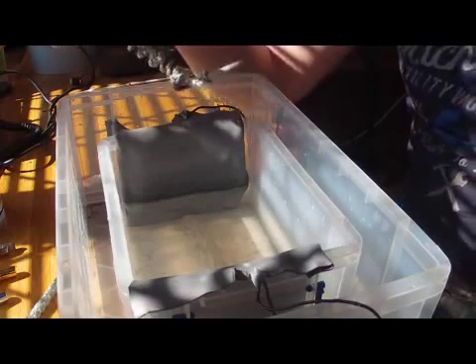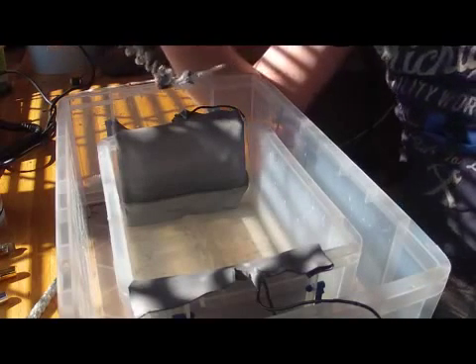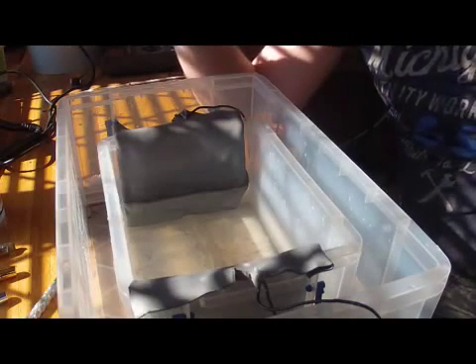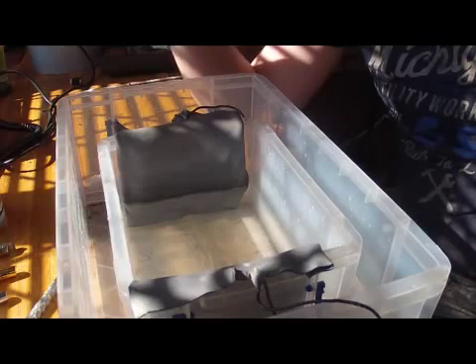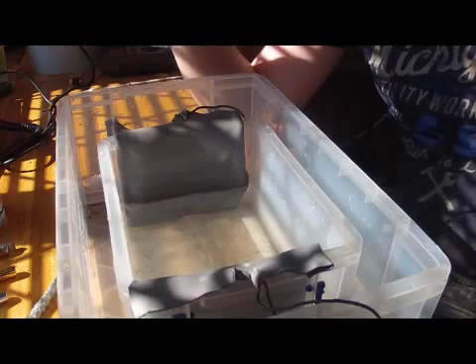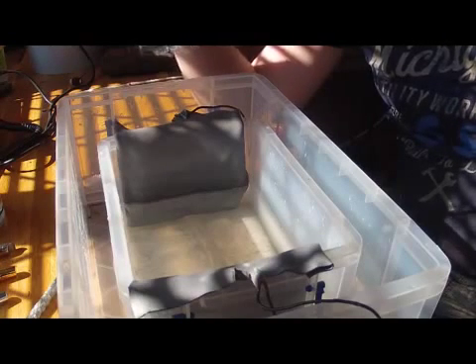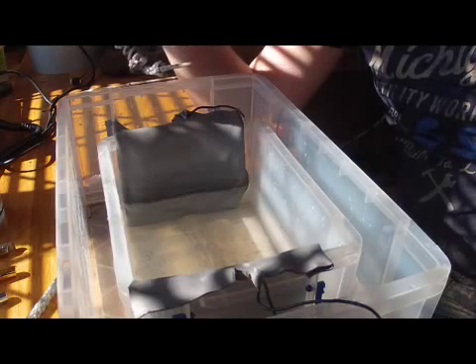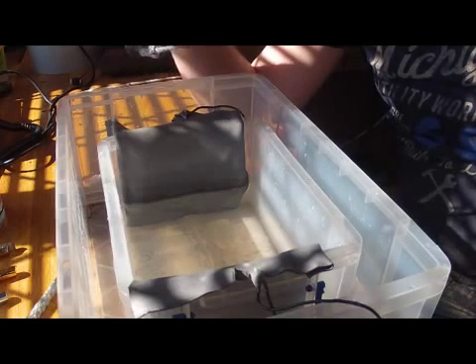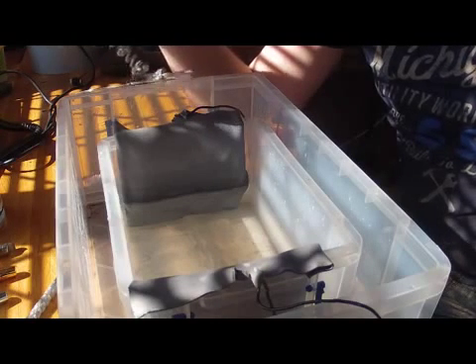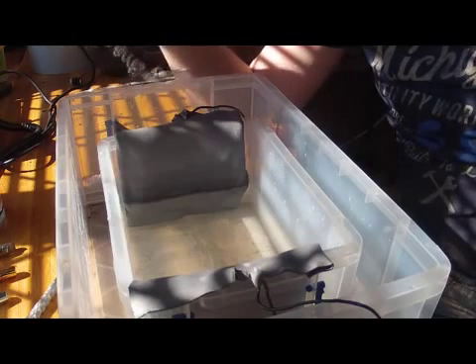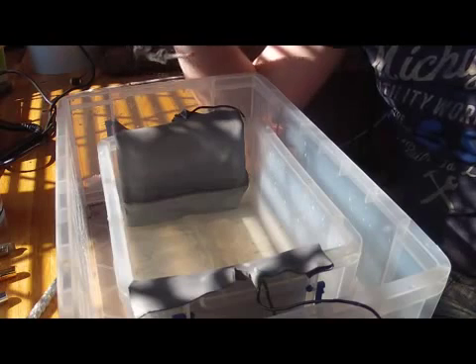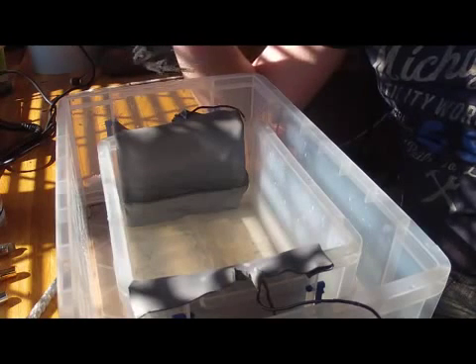Now that just goes to show you aluminium welding rods are not pure aluminium. And any other metals that go into this tank are going to corrode. So you can't put steel in it, you can't put brass in it, copper, or anything else. The only thing we're going to put in here is aluminium, with the exception of titanium.